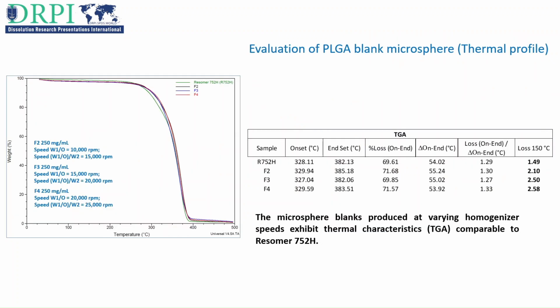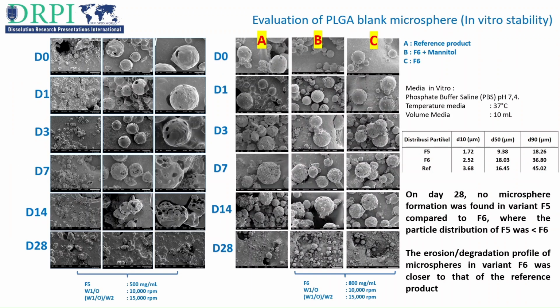These are the thermal gravimetric analysis curves that showed that blank microspheres prepared at different emulsification speeds had thermal characteristics comparable to pure PLGA. Both pure PLGA and blank microspheres exhibited the same degradation profile. It's called a single-stage decomposition with a mass loss of 69 to 71%.